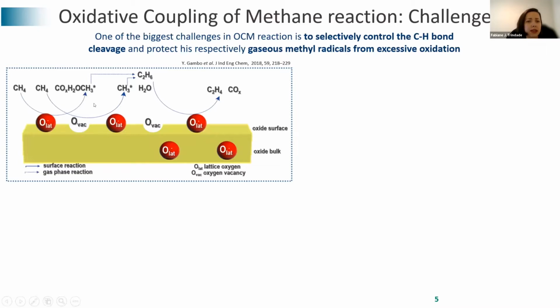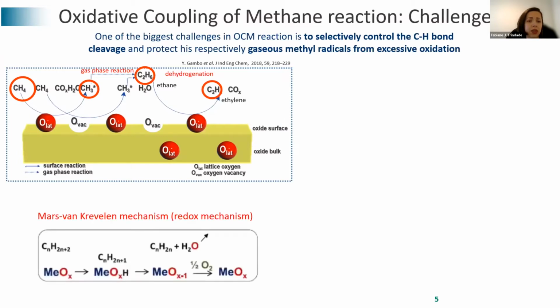This schema represents the OCM reaction on a metal oxide catalyst. First, methane activation involves the abstraction of a hydrogen atom from methane to produce methyl radicals. These methyl radicals are coupled in a gas phase reaction to form ethane, and then finally they are dehydrogenated to form ethylene. Studies have strong evidence that this mechanism can be described by the Mars-van Krevelen mechanism, where the oxidation reaction proceeds through the lattice oxygen of the catalyst.